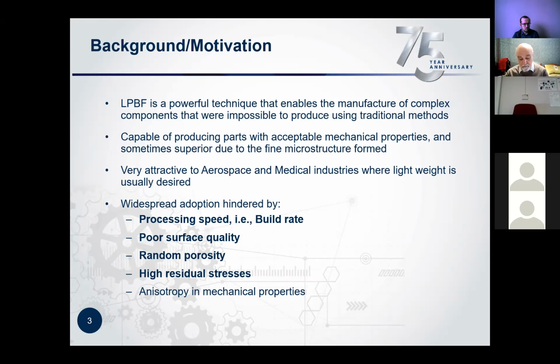And we have seen with ongoing research that the technology is quite capable of producing parts with somewhat acceptable mechanical properties. Okay, well, there's some controversies there, but we have seen it's capable of producing parts with acceptable mechanical properties, sometimes superior due to the fine microstructure that's formed during the manufacturing process, since you are using a very small molten pool, and this promotes a very fine microstructure. It's very attractive to the aerospace and medical industry for obvious reasons, due to its capability to produce complex components which are usually required in these industries. Of course, lightweight also being one of the requirements in the aerospace and medical industries.